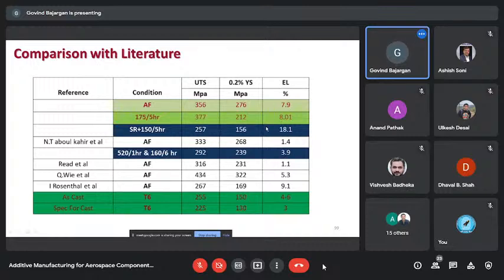as fabricated, in the as-printed condition. Then subsequently, when we devise different heat treatments, it gives you flexibility. If you go for different combination heat treatments, you can compromise on the strength, but your ductility comes out very good, 18% you can get. So this kind of freedom you get in AM, that is available.